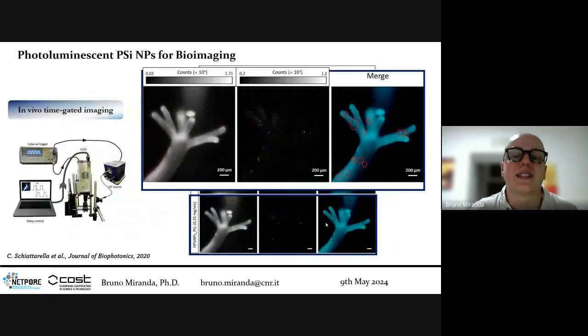To be sure they were inside, we also performed some in vivo time-gated imaging, in which you can see the autofluorescence of tissues has a much lower decay length, decay time, on the order of nanoseconds, while the nanoparticles have microseconds in decay of photoluminescence over time. As you can see, the photoluminescence of the nanoparticles remains inside. We can also see the overlap between the tentacles of the animal and the photoluminescence of the nanoparticles.